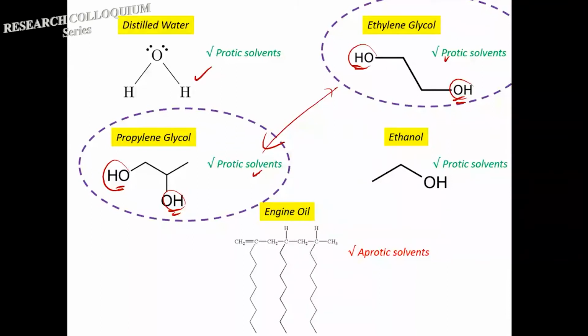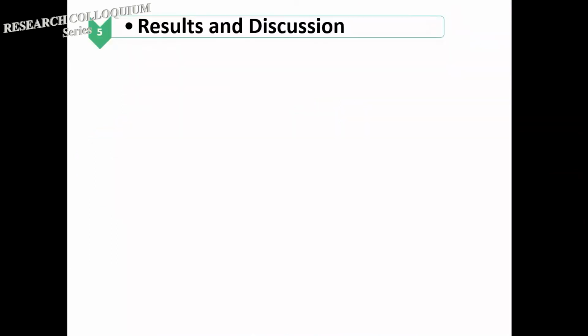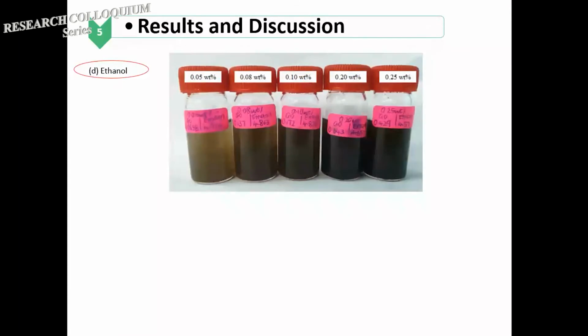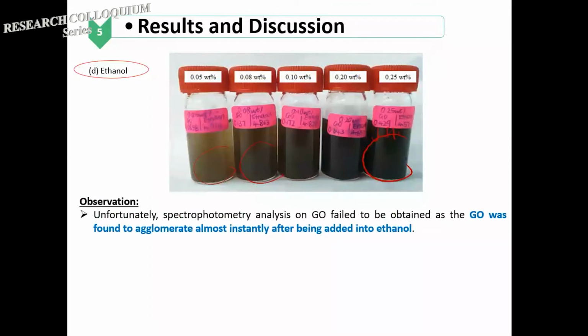Now the next one, we try working on ethanol. We try to see whether it's effective or not in ethanol. Unfortunately, this photo might not be that clear for you, but we found that after we put the graphene oxide into the ethanol, the graphene oxide went straight to the bottom already. It might not be clear in this image, but the nanoparticles straight away start to settle down, until we cannot even conduct the colloidal stability analysis because it's too fast, okay? The graphene oxide was found to agglomerate almost instantly after being added into the ethanol itself.